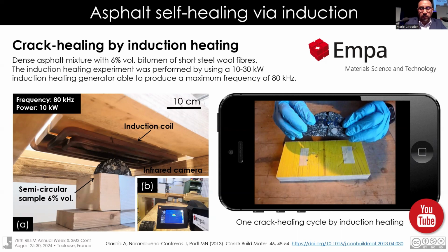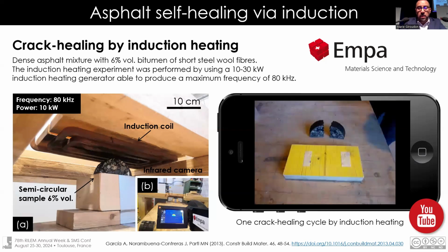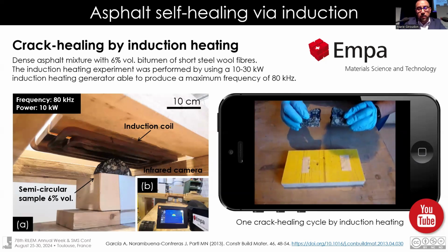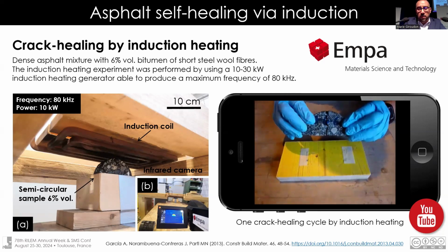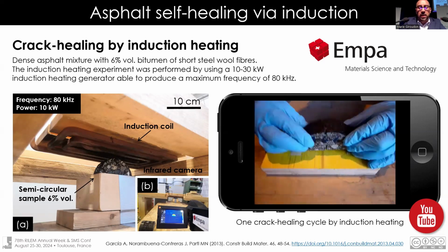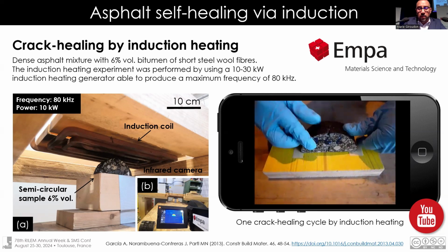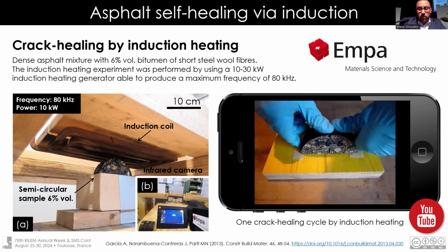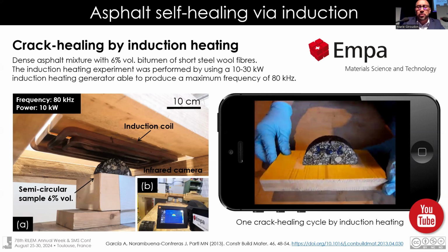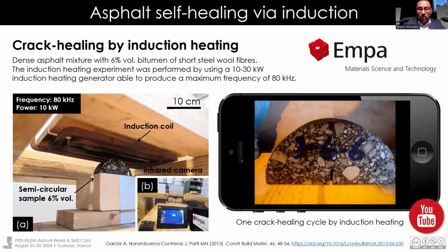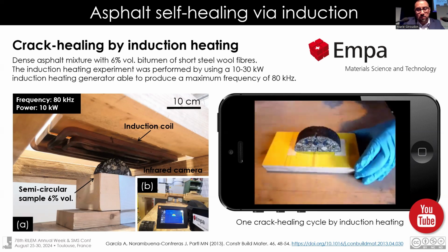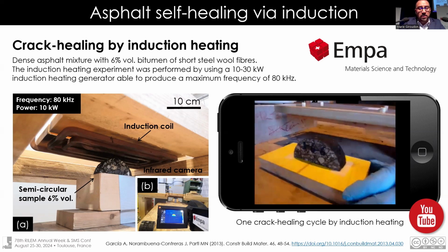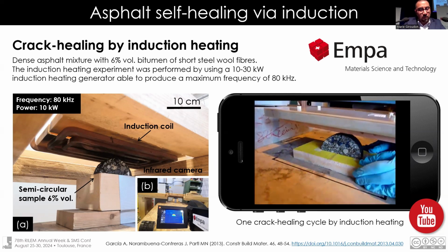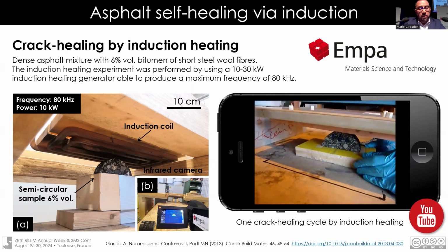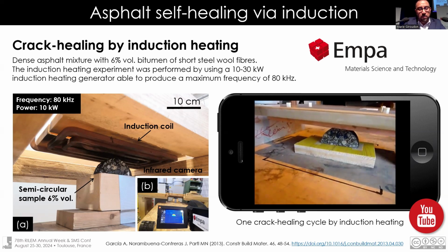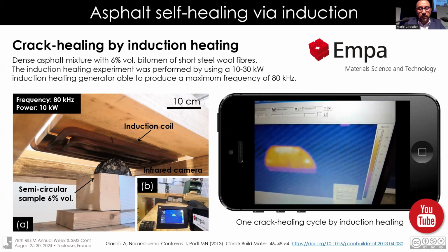Basically, to evaluate these materials, let me show you. First, they generate artificial cracking using mechanical testing, for example, 3-point bending tests. It's possible to use fatigue tests too, depending on your purposes. Then you piece together the sample parts in this sophisticated support, and then heat them under the induction coil without contact. After the sample is heated for a few seconds, you can stimulate the bitumen inside the material, and you can promote the flow autonomously inside the material.